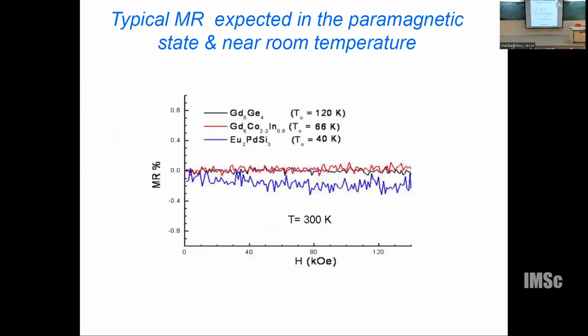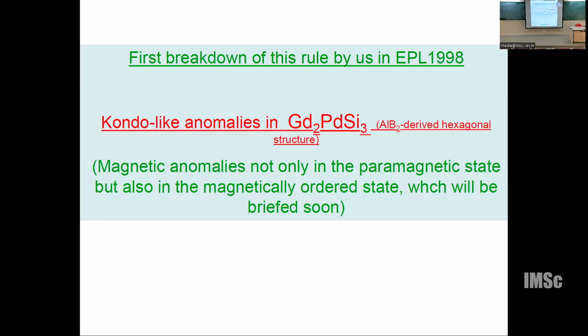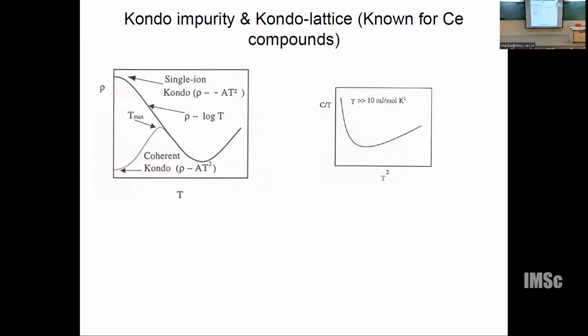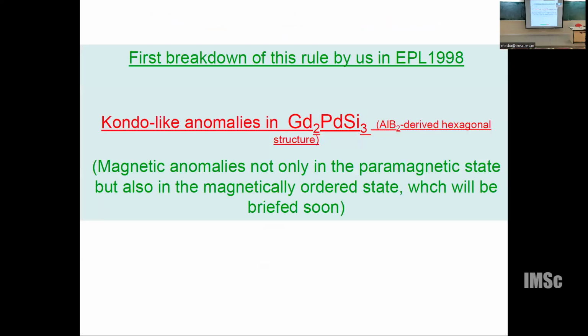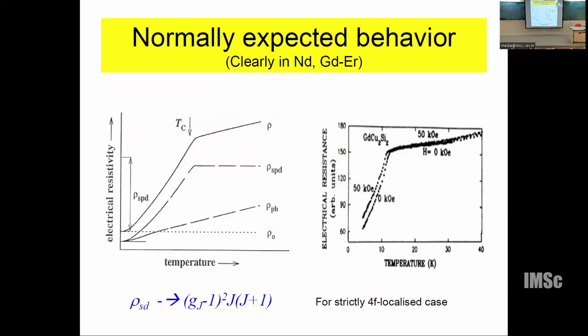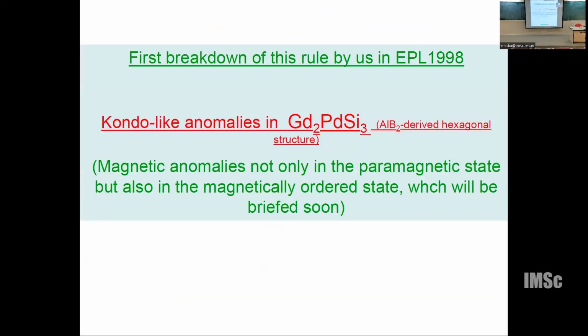In contrast to that, in cerium compounds, as I told you, this is what you find. The resistivity has a minimum here. Of course, if you have a large number of cerium ions in the lattice, you will see a decrease. That is called coherent effects. Don't worry about it. What is important is that if you have heavy fermions, you will see a minimum here. If you see a Kondo effect, you see a minimum here. So in this compound, we observed for the first time the breakdown of this rule. Which rule? This rule. This is textbook material. This rule was broken for the first time in 1998.